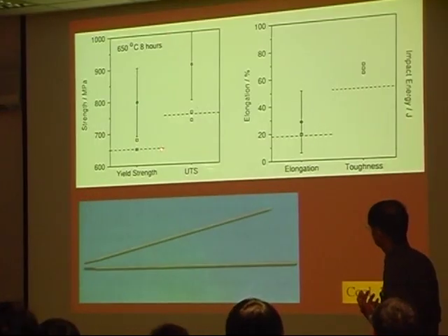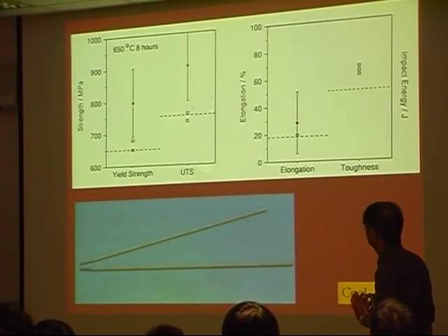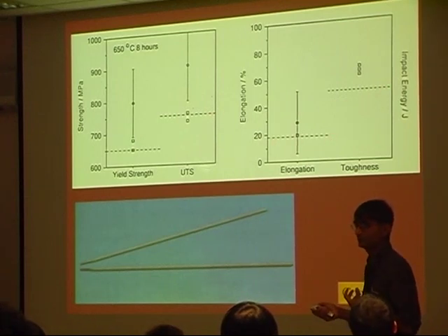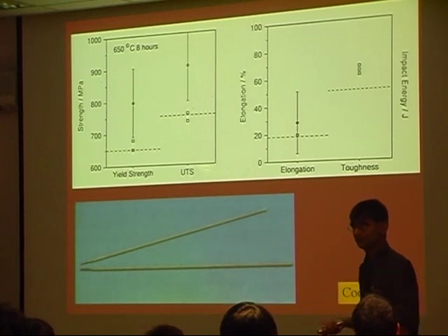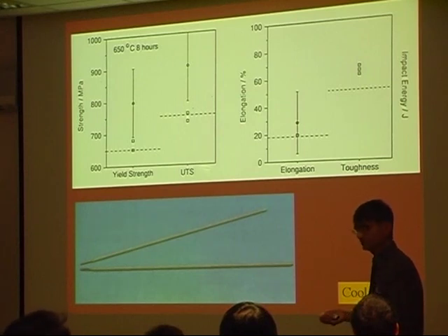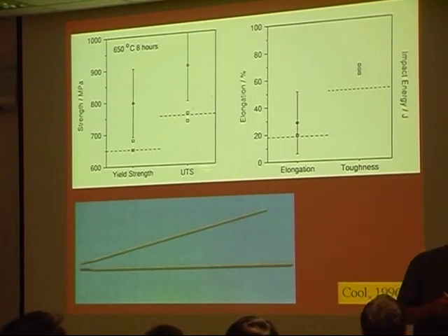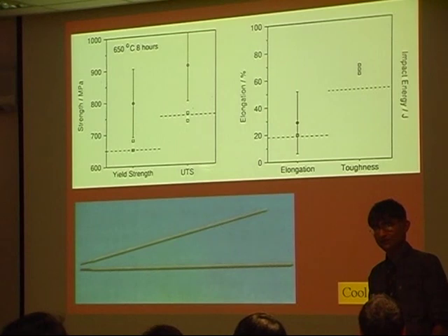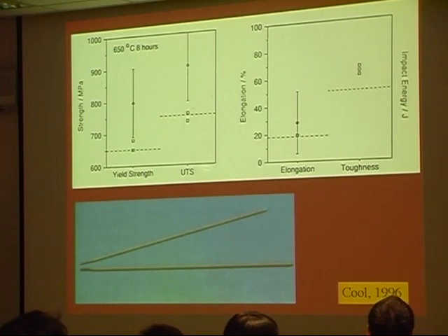When we started this particular project, the engineers set the targets that we must have this much strength, this much ultimate tensile strength, this much elongation, and this much toughness. Okay. And using a whole variety of models, we made a prediction. And then they designed the welding electrodes. And when the welding electrodes were actually made, in every single case, we achieved the engineering properties without doing any experiment. Okay? But being in a university, we did more experiments than was necessary. Okay? And we came across a problem.